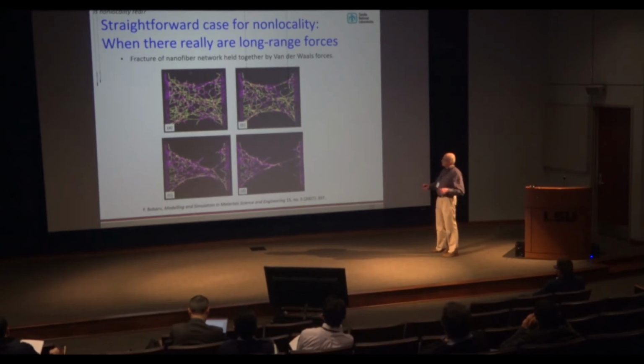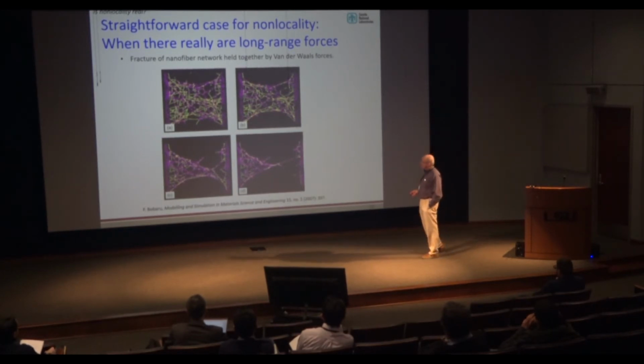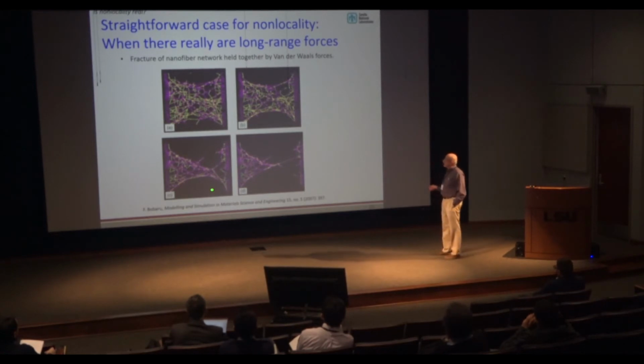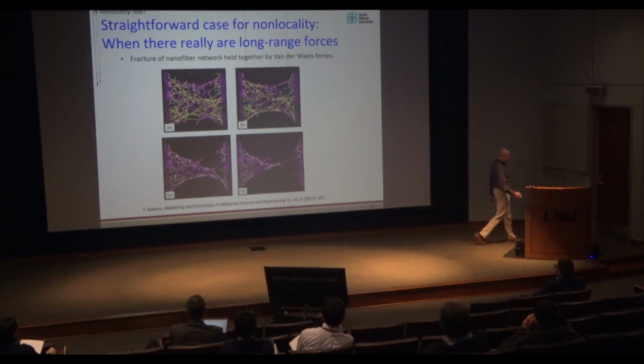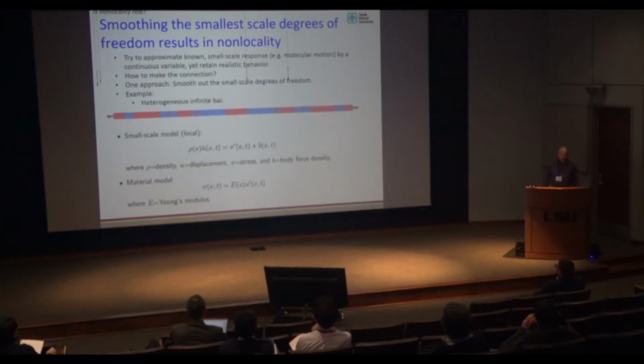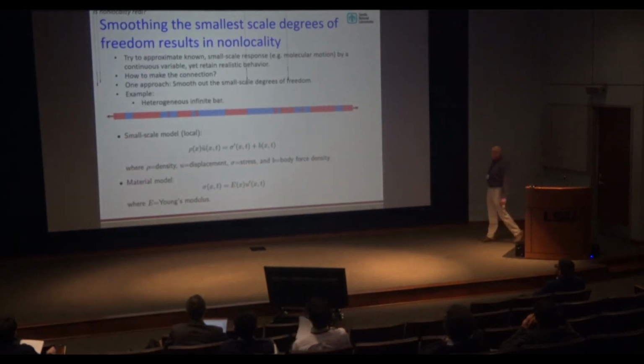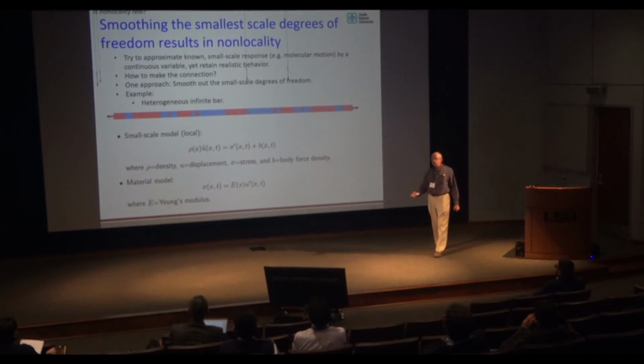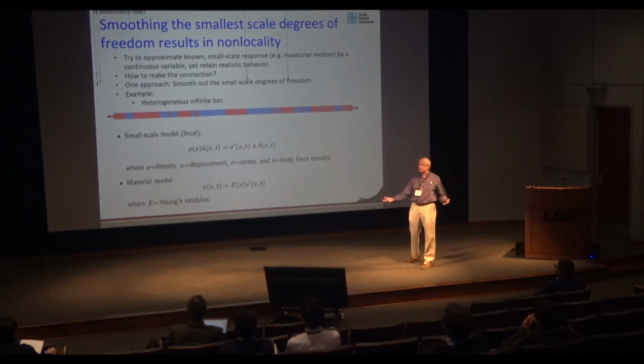and is basically a van der Waals type force. So as you stretch on this nanofiber network, the strings individually tend to remain intact, but they separate from each other because the van der Waals forces are relatively weak. So Florin developed a material model that included both the internal forces and the forces between these fibers with a very reasonable looking result. So that's the most straightforward case. What's a little less straightforward is when there is not an obvious physical field that provides these interactions over finite distances.